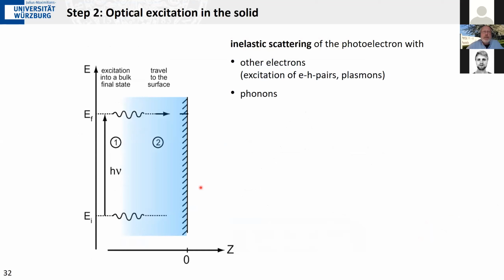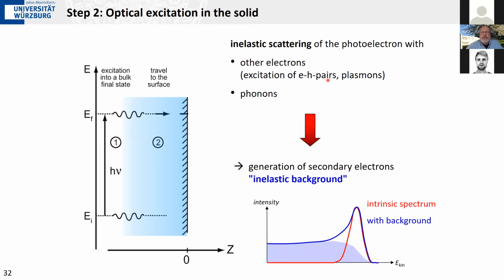Okay, so we have the first step. We had the excitation in the volume. Now the electrons travel towards the surface. And as I mentioned before, the photoelectron will experience, or some of them will experience, inelastic scattering events with other electrons, giving rise to interband transitions, excitation of electron-hole pairs, and in particular plasmons, so coherent oscillations of the entire electron system, and they may also generate phonons, and by that lose typical phonon energy. And as a consequence of that, you will have a lot of photoelectrons that have lost their energy and will appear at lower kinetic energy, and give rise to a background of secondary electrons.